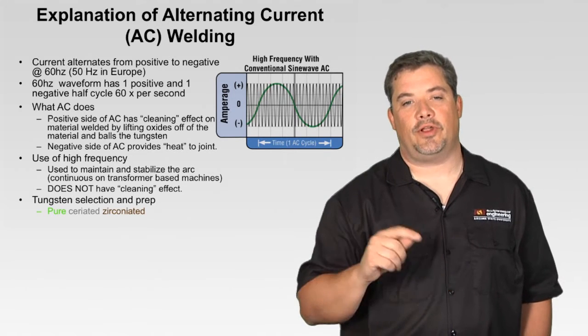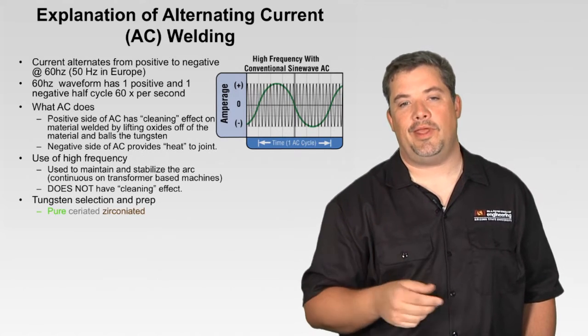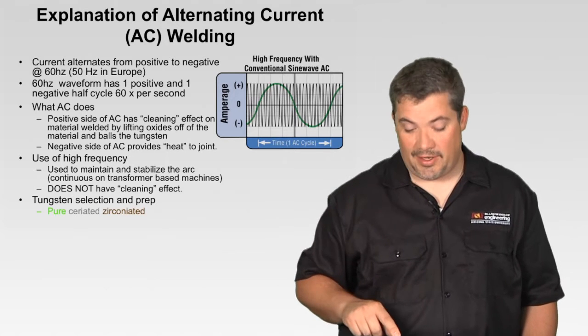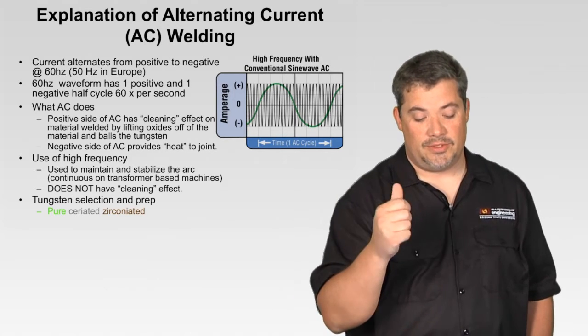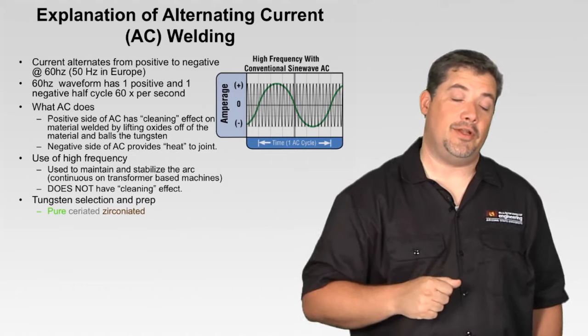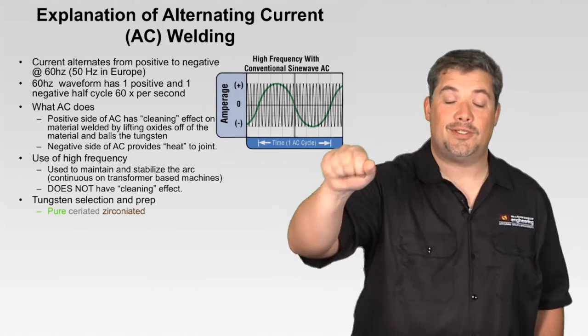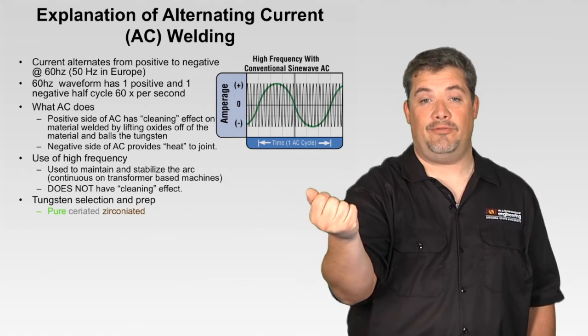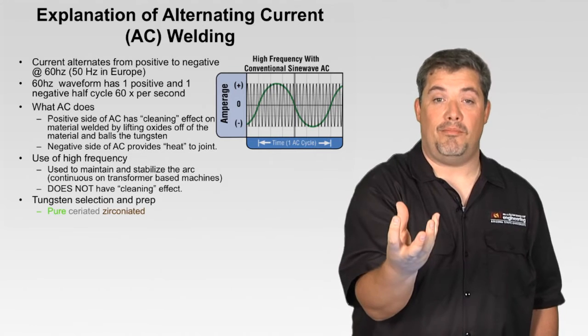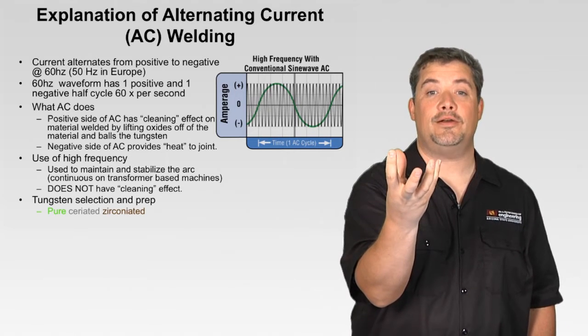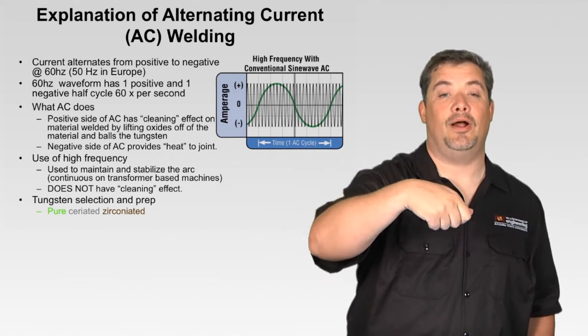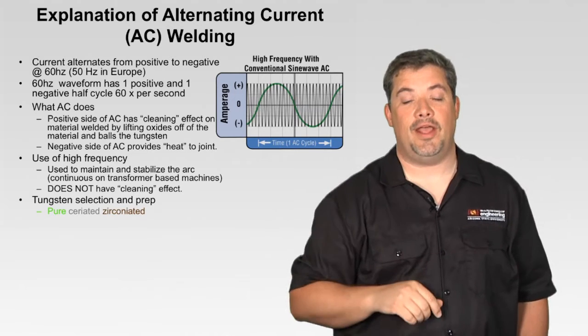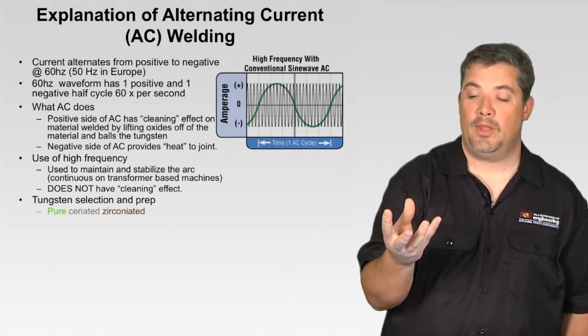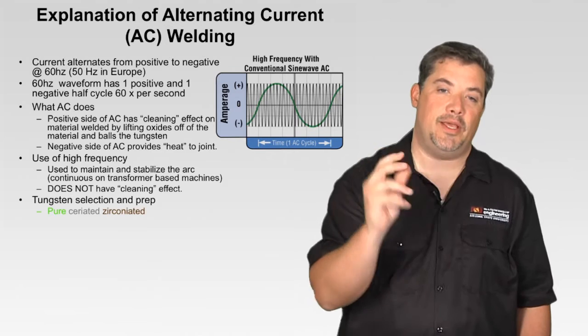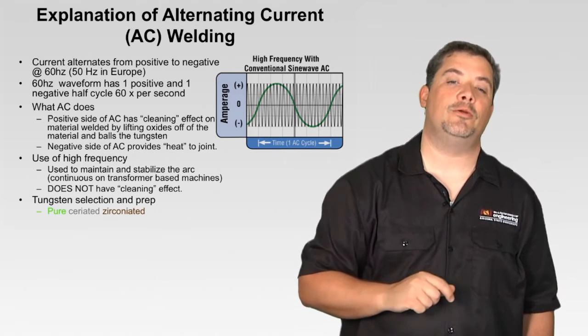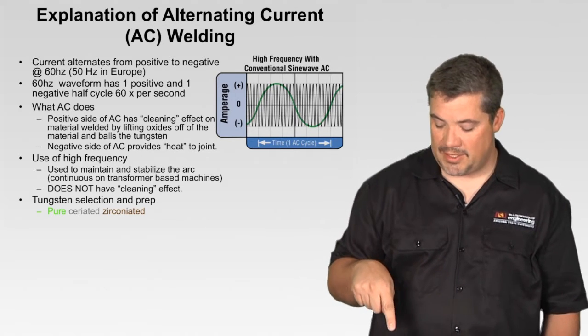Tungsten selection for conventional AC: pure and zirconiated. We can use the ceriated and lanthanated too, except when we use the ceriated and lanthanated on conventional AC machines, we have to switch our machine to electrode positive and strike an arc and make a really big ball on that tungsten, then go back to AC to weld with it. Not so on advanced machines, where pure tungsten makes the size ball it needs based on the current it's carrying, so that's why pure is so good on conventional AC.